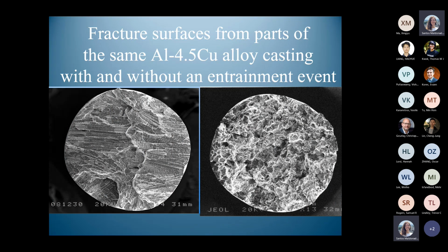And here's a typical, I think it's a 6 millimeter diameter test bar, which has been fractured. And this is the fracture surface. And what you can see is that here the dendrites have grown and have pushed the film ahead here, and the dendrites also grown and have pushed it here. And so this little mountain range down the middle is all the spare oxide film that's been pushed ahead of the two lots of dendrites as they've grown towards the center and just piled up the film in the middle. And so these are really quite large crystals,